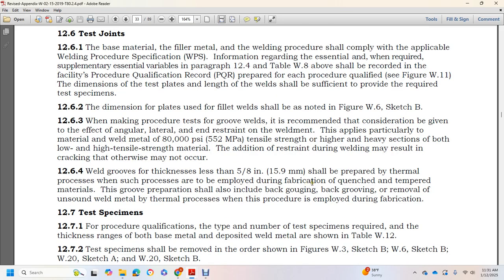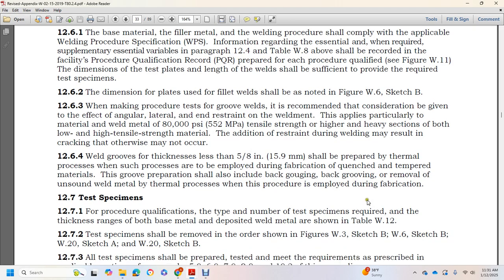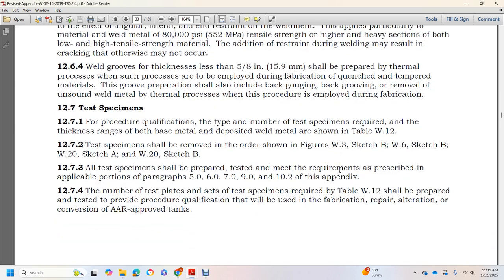The test for the process employed during fabrication of quenched and tempered material of the groove preparation shall include back gouging, back grooving, and removal of the unsound metal with the thermal process for the procedure employed during fabrication. Test specimen: for procedure qualification, the type and number of test specimens required with the thickness range of both base metal and deposit of the weld metal are shown in table W12. Test specimens shall be removed in the order shown in figure W3 sketch B, W6 sketch B, W20 sketch A, and W20 sketch B.